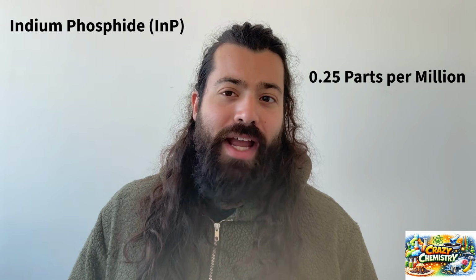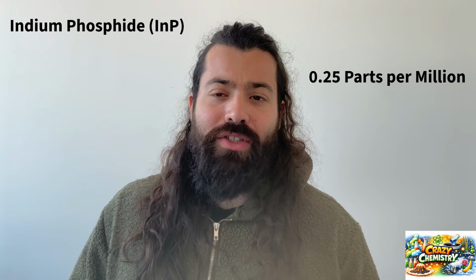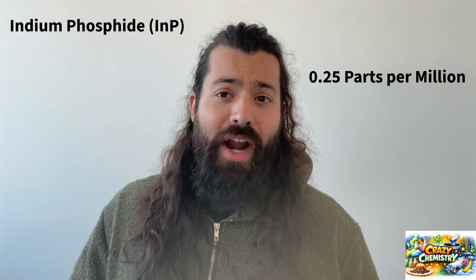And here's why the supply chain story is so important. Indium is rare, about 0.25 parts per million in Earth's crust. It is mostly recovered as a byproduct of zinc mining. China refines approximately 60% of the world supply. Then you need ultra pure phosphorus and you melt them together at 1000 degrees Celsius under high pressure, and you have to grow a single crystal, atom by atom, without inducing any defects in the process. Then you slice the crystal into wafers, then epitaxy, growing thin layers on top, 1 atomic layer at a time. Then the photonics, then packaging. Every single step is harder than silicon, and every single step is concentrated in fewer hands.